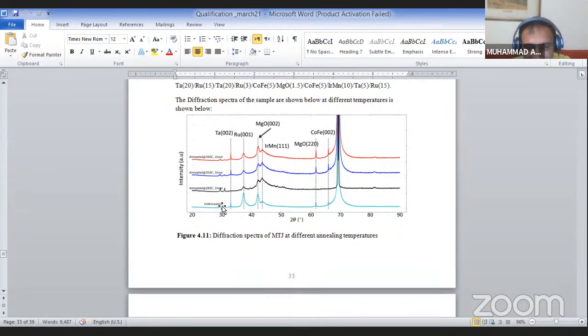I did not see in detail these peaks. I want to see only the peaks of the MgO, how I grow this MgO. But it would be interesting to at least check, because the X-ray diffraction is very sensitive, and then you may find something interesting. I'm just guessing. The important thing there is that peak just above 60 degrees.